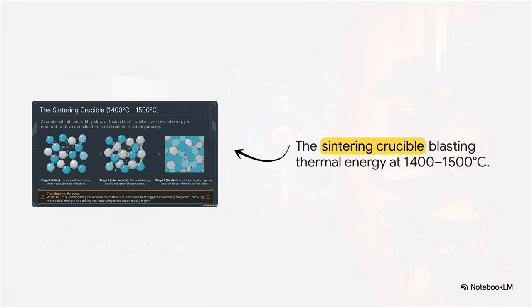Here's why. Zirconia has incredibly slow diffusion kinetics. So forcing these loose powder particles to actually bond together and eliminate all that empty porous space requires massive thermal energy. We're talking between 1400 and 1500 degrees Celsius. The material has to go from loose particles forming small connections to locking tightly together. But here is the sintering paradox.